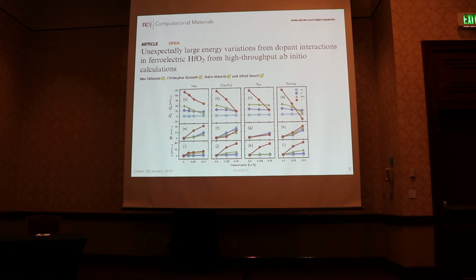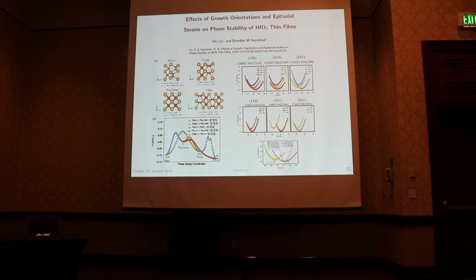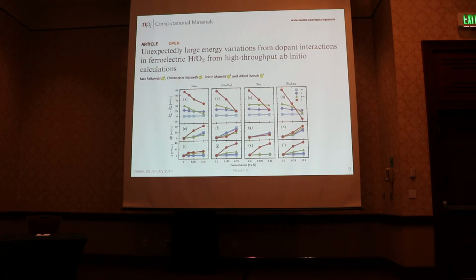In this study, they tried to understand, they actually emphasized unusually large, but I don't know that I'm completely won over by that. What they actually found was that no matter what they doped it with, still the nonpolar phases were the most stable. So nobody's really explained, even by doping yet, the stability of the polar phases. But they did show that if you dope it, you can stabilize phases other than the monoclinic phase. So that part is clear. So we know that it's fairly easy to make this orthorhombic phase, or maybe rhombohedral phase, by strain or by doping, but making them polar is still an open question.